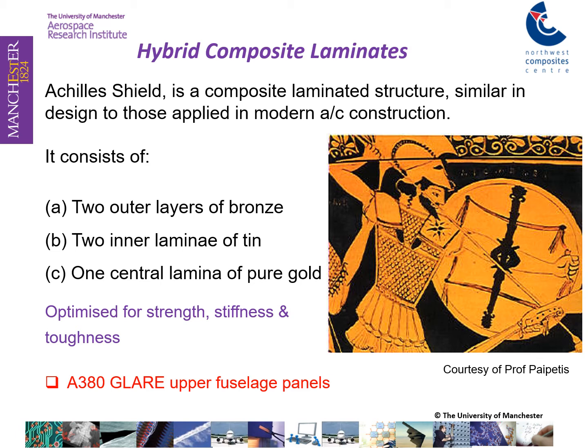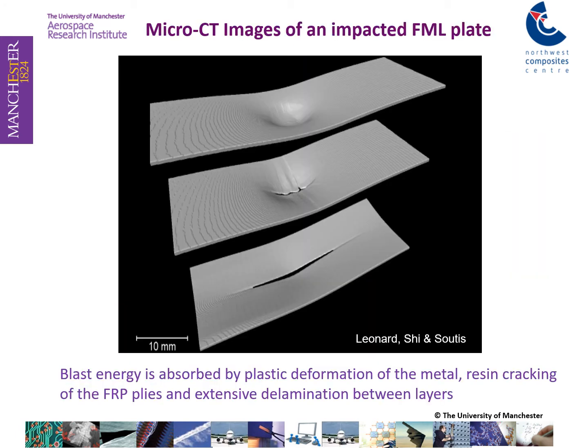The Airbus A380, of course, the upper fuselage panels are made from GLARE, which is a multi-layered construction of aluminium plies and glass fiber reinforced composite. Here we can see a micro CT image of an impacted fiber metal laminate where the blast energy is absorbed by plastic deformation of the metal, extensive splitting and resin cracking of the fiber reinforced plies, and many delaminations between the neighboring plies. But you don't get perforation.